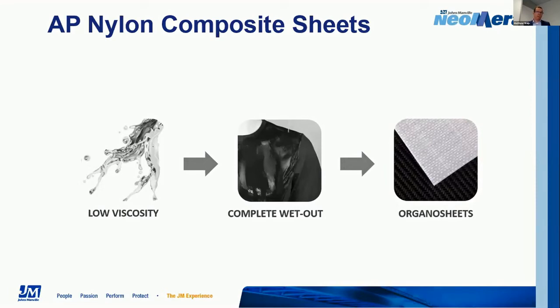And the resin system at that temperature has a very low viscosity. It has basically a water-like viscosity to it, which has a huge benefit when we start to think about application into the reinforcement. And so I use the analogy pretty regularly that if you have a fabric like a jacket or a coat and you pour water on it and it just soaks into the fabric, that's what's really enabled with using such a low viscosity system, that full wet out of the fabric. And then once the resin system is within the fabric, it's polymerized into the nylon.